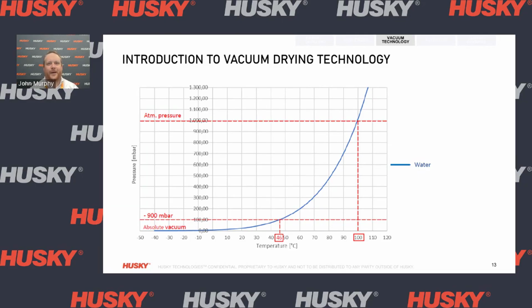Now, I would like to introduce vacuum technology. Unlike desiccant drying, which uses heated air and desiccant beads to absorb and remove moisture from resin, vacuum drying removes moisture by lowering the pressure, allowing water to evaporate at lower temperatures. As you can see in this chart, water has a boiling point of 100 degrees Celsius at atmospheric pressure. This is something that everyone is familiar with. What is interesting is that when you expose the water to a vacuum, you are able to lower the boiling point. You can see here on the graph that at minus 900 millibar, the boiling point is reduced to around 46 degrees Celsius. This reduced boiling point is the key to vacuum drying technology.